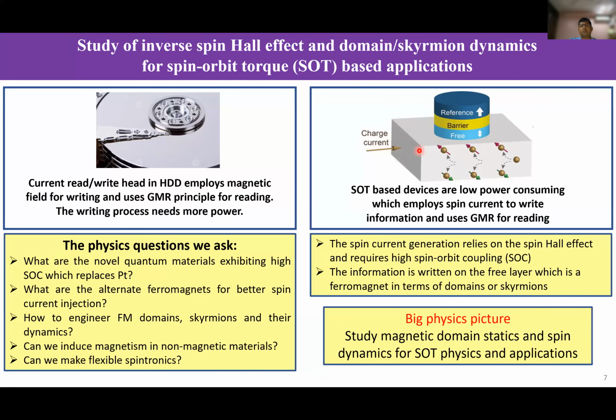Now, as you see, these kinds of systems have basically two components, and you need to ask a few questions, like what is the best material to make this charge to spin conversion using spin orbit coupling. Obviously, the heavy metals like platinum are the most preferred material because they exhibit high spin orbit coupling, but we don't want devices made of platinum for obvious reasons. So people are looking for other alternatives, and that is one interest.